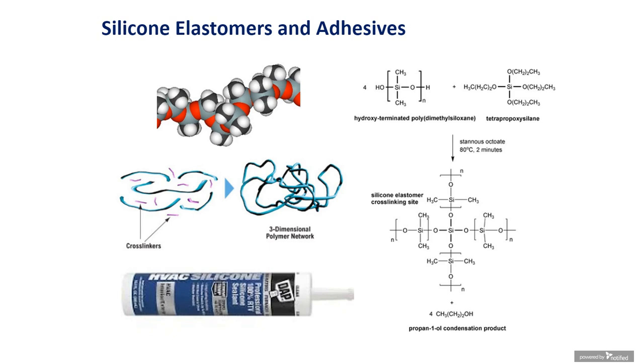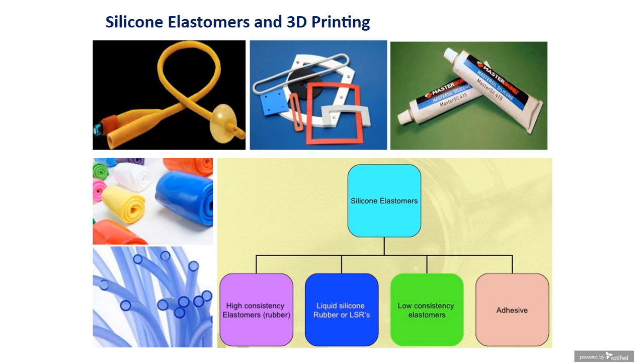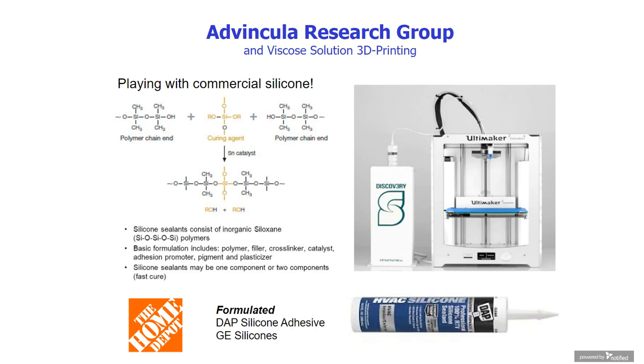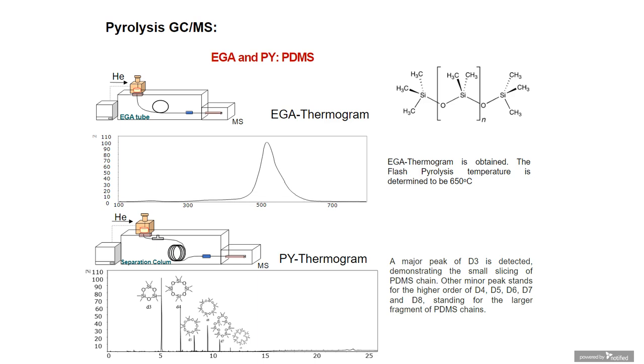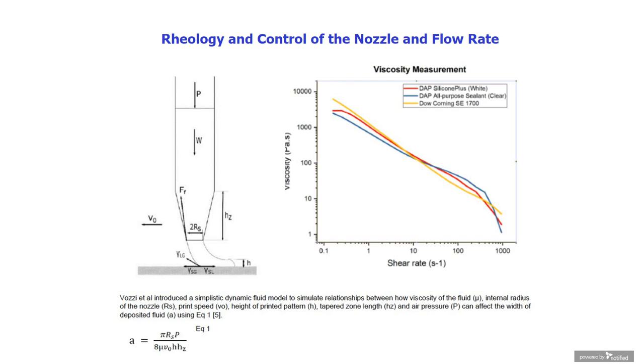So in this case, the silicone elastomer we use, again, was a commercially available silicone from Home Depot. And silicone is a thermoset elastomer based on the cross-linking of the siloxane units in various forms without going into silicone chemistry. We then 3D printed them using a CNC movement. And again, by reverse engineering with Pyrolysis GC, we confirmed that the majority composition of this material is really a polydimethyl siloxane with the corresponding peaks of the cyclic oligomeric fractions that was confirmed by the spectral library.